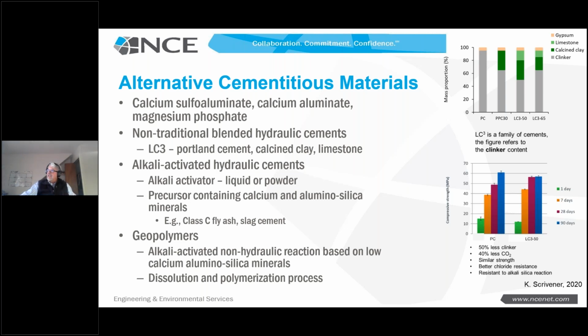On the right are some figures that represent the LC3 formulations that can occur. This is something I was talking to Prashant a little bit about. He said there are already a couple of cement plants in India in full production with LC3. It is a possibility of using common, abundant materials to reduce the clinker content of our cement by 50% or more, which is a significant step in the right direction.